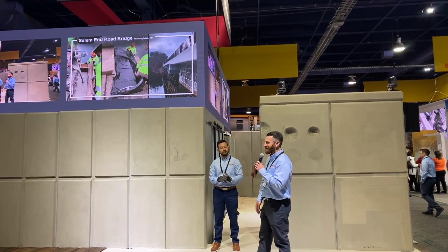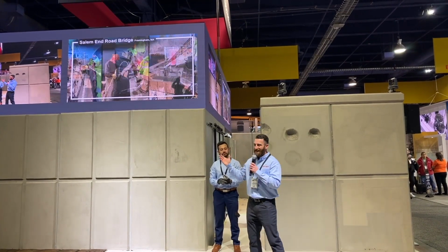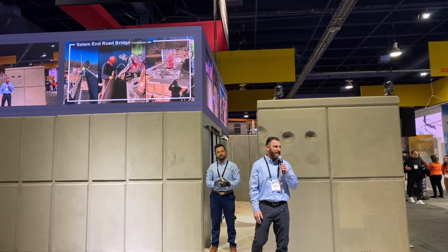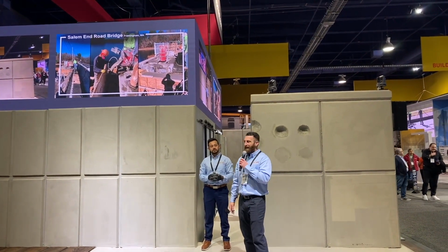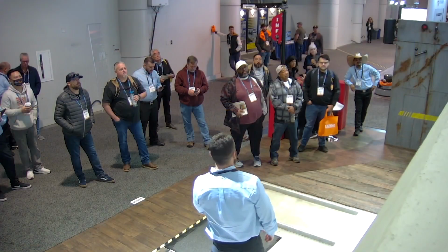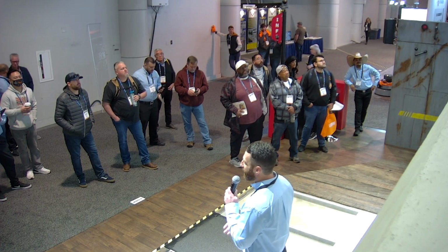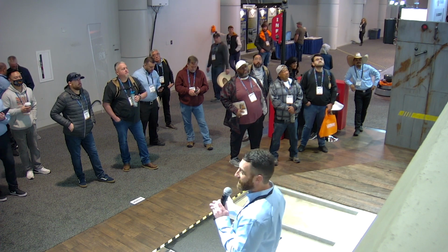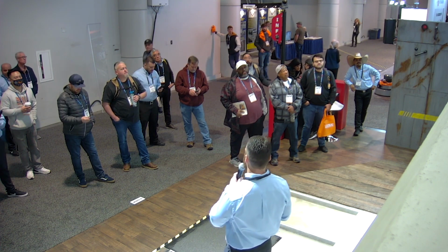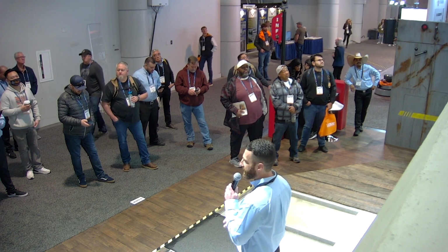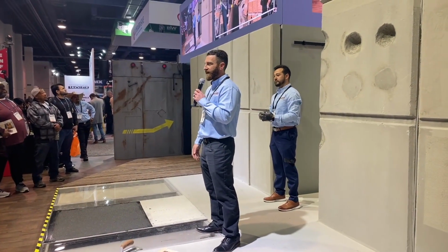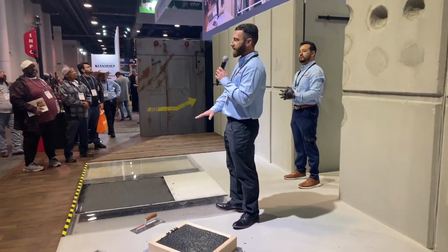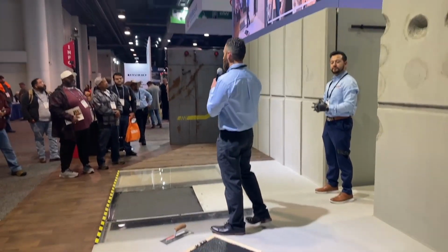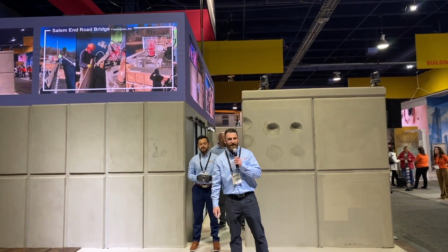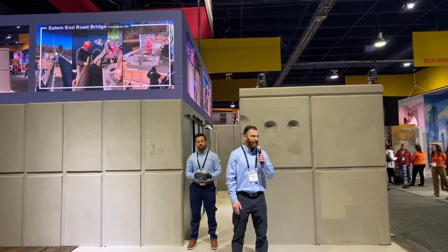And the Salem End Road Bridge, this bridge was built something like 100 years ago, and it had been repaired multiple times over the years, but it was in desperate need of repairs again in 2019, and they specified the DOT concrete mix. And the big challenge about that project is that they had very hot temperatures and very cold temperatures. So when it was hot, they had to use the set control, which is our set retarding admixture, to give it extra working time, and they also used cold water. And when it was cold, they had to warm the surface with warming blankets, and they used a hot water heater to kick off the reaction a little bit faster. The repairs turned out great, and they expect that bridge to last for another 20 years before needing more repairs.